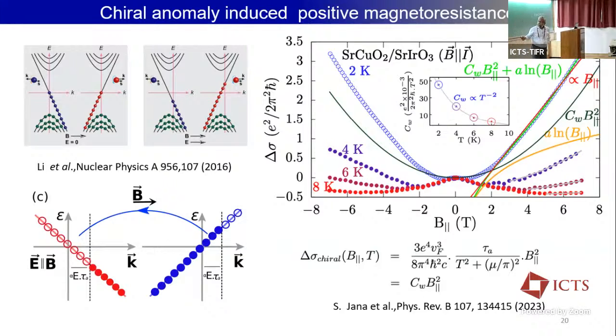Because what we understand so far is that when we put in an antiferromagnet, the chiral relaxation time tau A increases because the impurity scattering is decreased. And once impurity scattering is decreased, the chiral relaxation time increases. Because of that, you get more contribution to the chiral anomaly conductivity when you have an antiferromagnet. But in a bare SrIrO3, the chiral relaxation time is not like this in the case of the bilayer. So we see the trivial magnetoconductance.